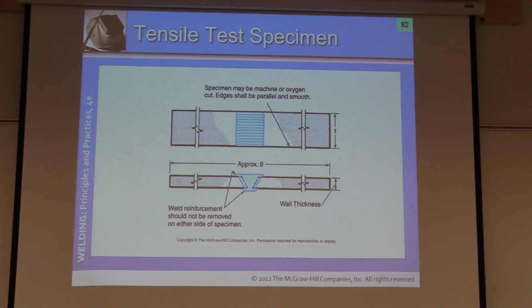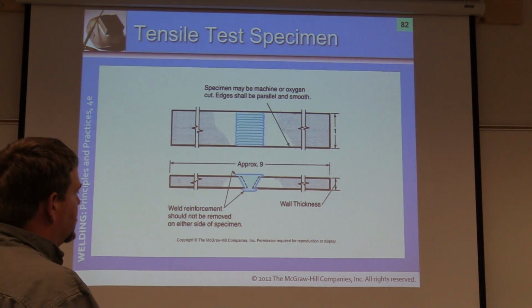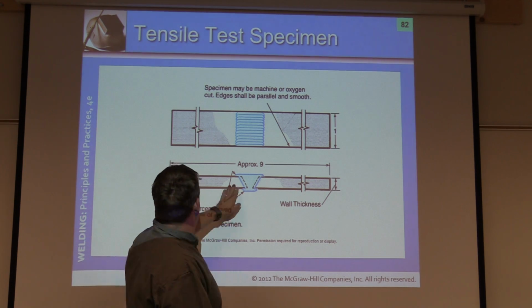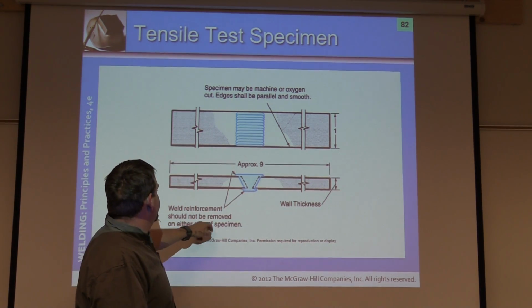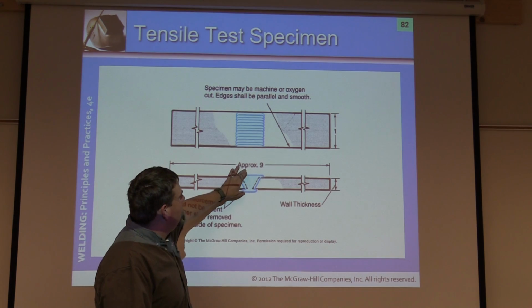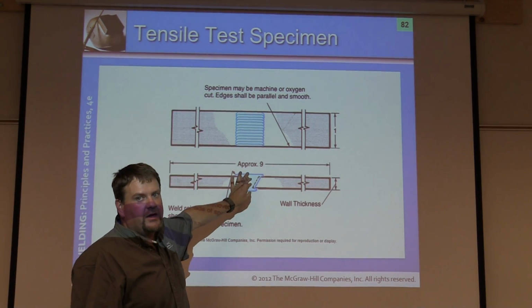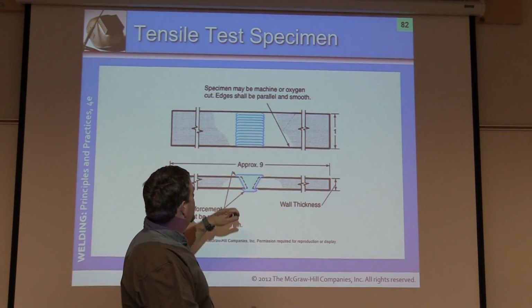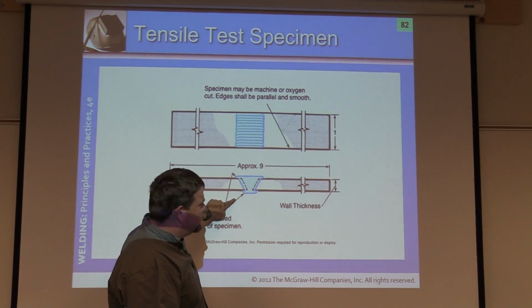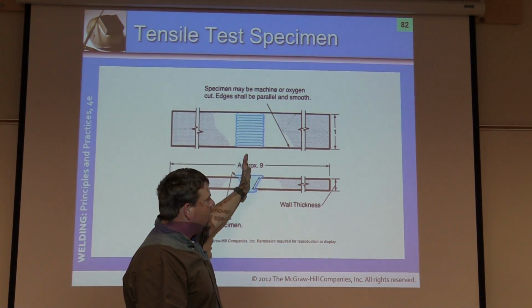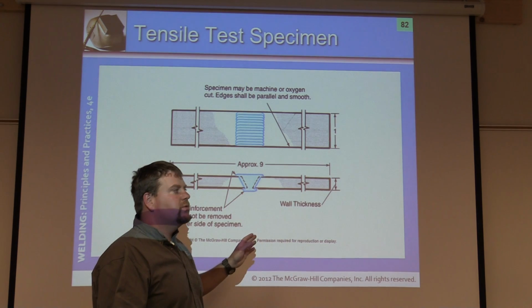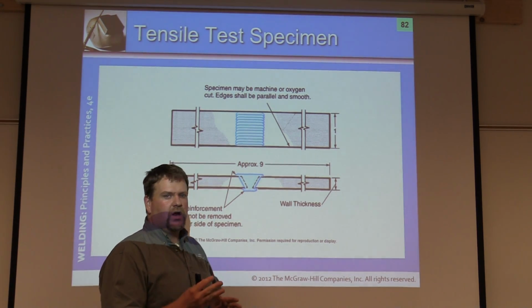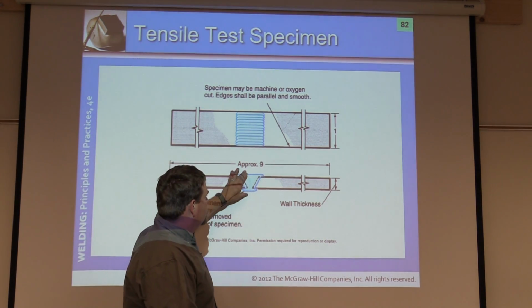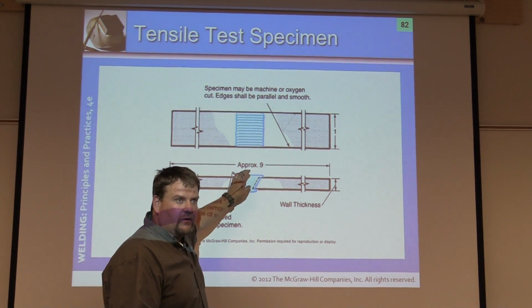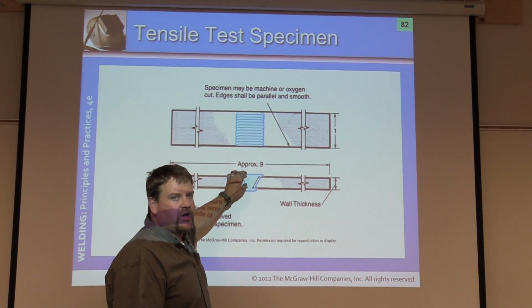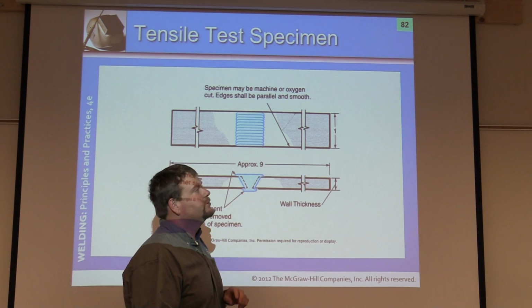Now this is not a reduced section tensile, this is a full strength tensile. So we don't touch anything. The weld reinforcement should not be removed on either side. You pull it apart. This is API code, okay? It has to break in the base metal, or if it does break in the weld, it needs to exceed the tensile strength of the pipe, and also there cannot be any visible discontinuities within the weld where it broke.